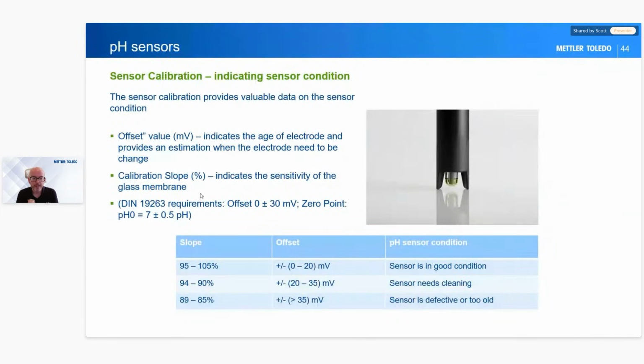So when we do a calibration, we've taken our system, we've stored an electrode correctly, we've made sure it's clean, ready to go, we've taken a calibration, an offset, an adjustment, and here's what's happening. We've done a sensor calibration, and it goes back through this offset and calibration slope. Here you can see the designation that at Mettler Toledo we decide is a good or a bad calibration. If it's between 95 and 105% and 0 to 20 millivolts, we say everything's good. And in our meters, you will see a little symbol that looks like a telephone signal with 3 bars. These 3 bars on our meter are showing this type of thing.